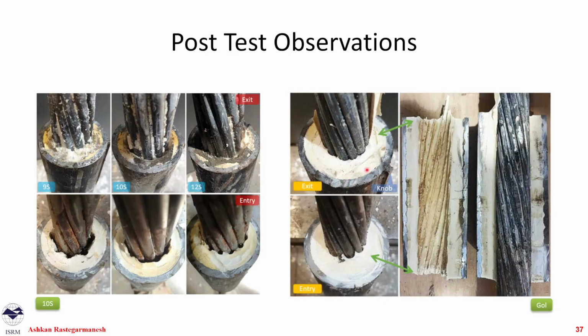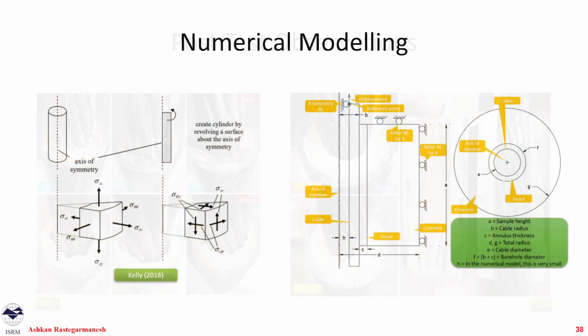This is the same observation for resin. Obviously, resin is more ductile, so we are not seeing that brittle failure, but you see the mismatch of the patterns of the cables compared to the lugs they have on resin. And on the top, we see the damage on the top. And again, in terms of the sharpness of these lugs and ridges, we see that as we go towards the exit point, they become sharper and the damage is less.